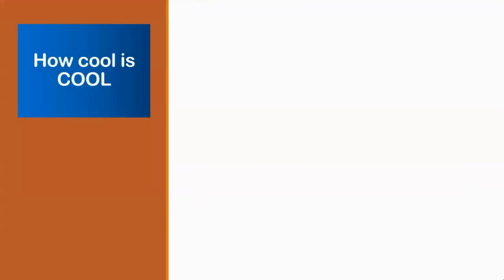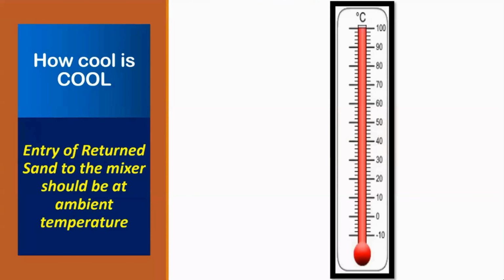So let's talk about how much to cool the sand. Let's say how cool should be cool. Entry of return sand to the mixer should be at ambient temperature. That's our aim. So it was very hot. The temperature of the metal was 1400 plus. And the sand would have reached something like 800, 900 degrees. And from there, by the time it comes to the cooler, it will be still very hot when it is all mixed up with unreacted sand. Then the temperature should be something around 80, 90 degrees.